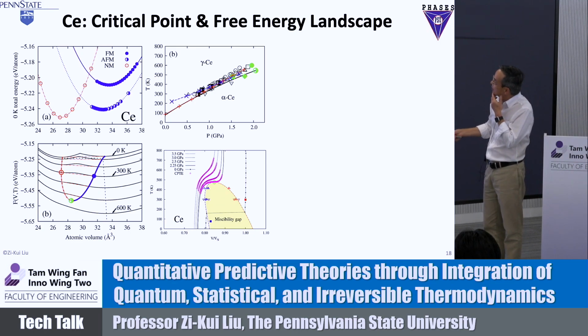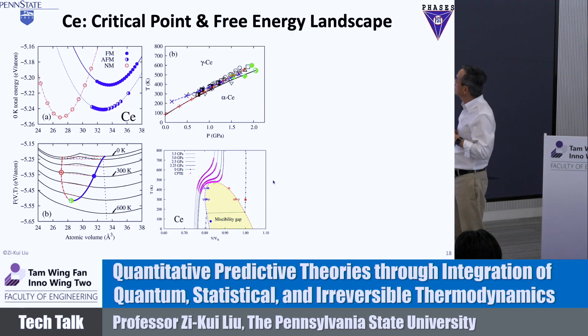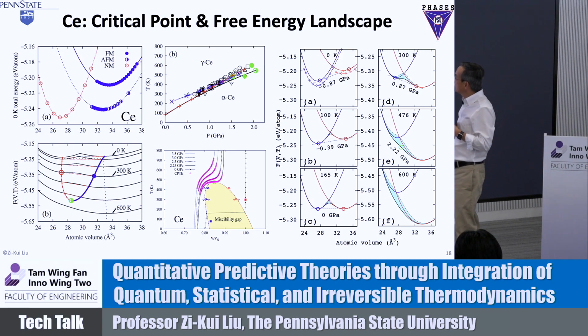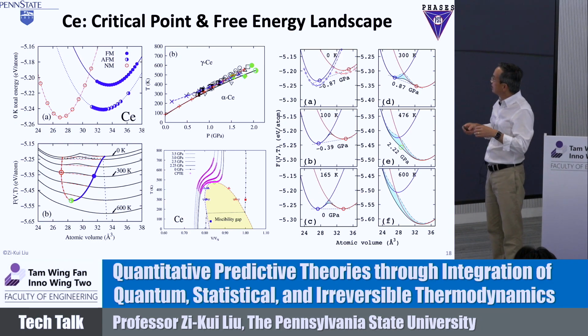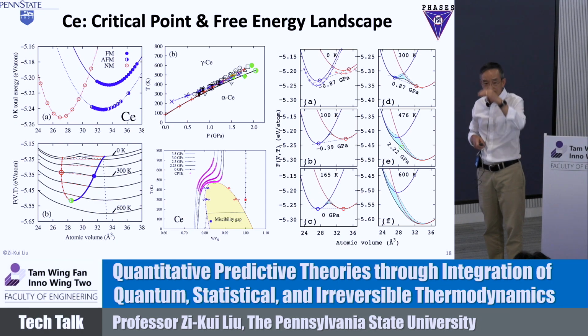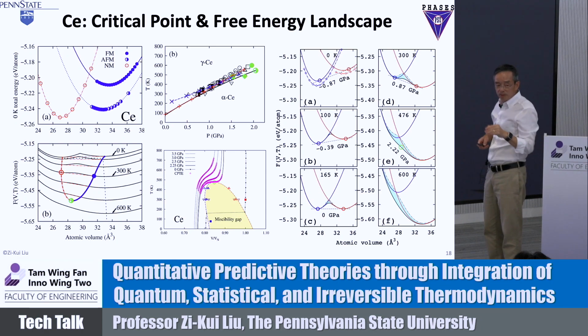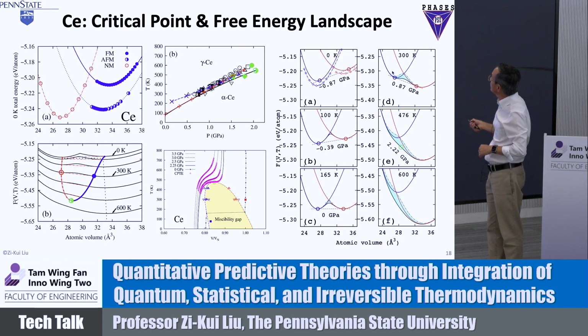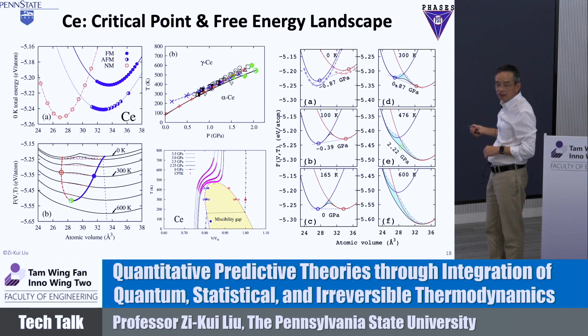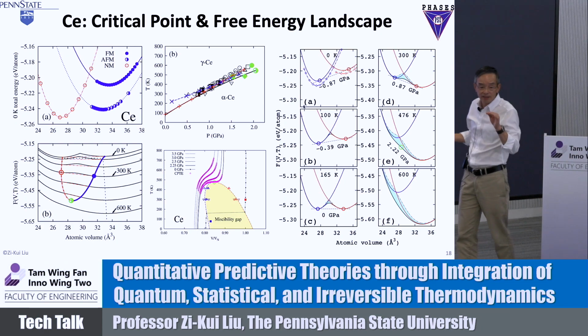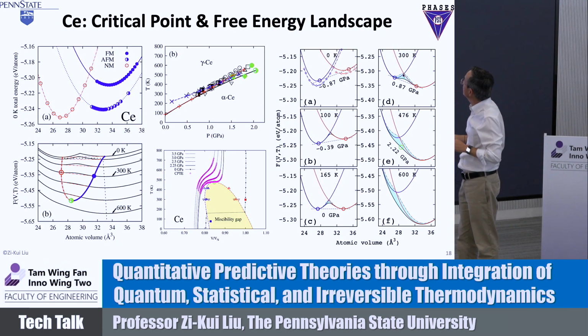You can see the phase boundary here, where the two symbols are the phase boundary. You can see the prediction from these only 3 configurations predicts the critical point and the phase boundaries reasonably well. And you can figure out what happens at different temperatures. The shaded area is the extra entropy put in. The individual lines are from quantum mechanics, and the shaded area in the middle is the configuration entropy. What do you see? You can predict the barrier between the 2 states, not configurations anymore, 2 states, because each state is a combination of many, 3 of them, with different probabilities.